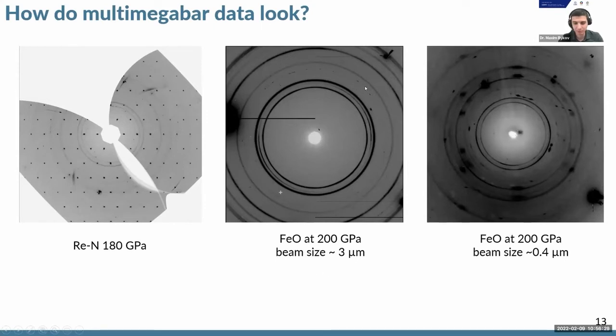This is the diffraction pattern of iron oxide at 200 GPa, collected at the beamline, I think ID27, with a beam size of 3 microns. And here we see mostly the diffraction from rhenium and a huge peak from diamond. And there are a few tiny peaks from iron oxide. However, when we bring such a sample to a beamline where we can focus the beam down to, for example, 400 nanometers, this was the beamline ID11 of ESRF, the same sample would reveal much different features in the diffraction patterns. So we see nice lines of the new FeO phase, which was further solved and refined to quite well residual values.